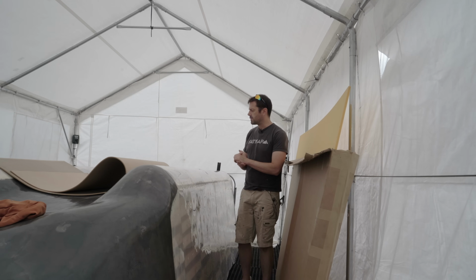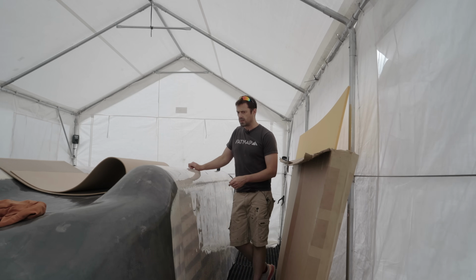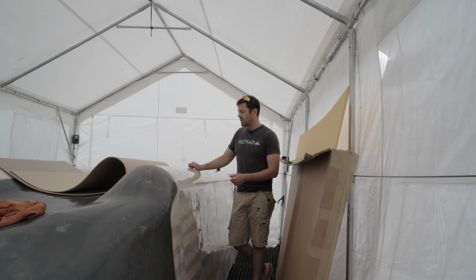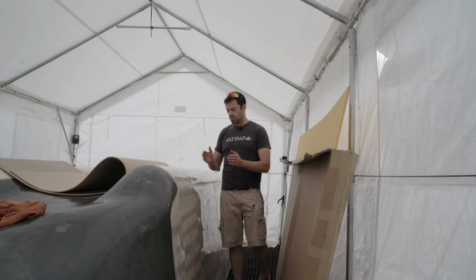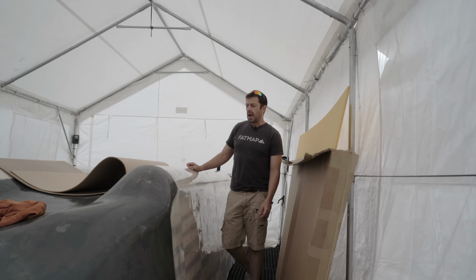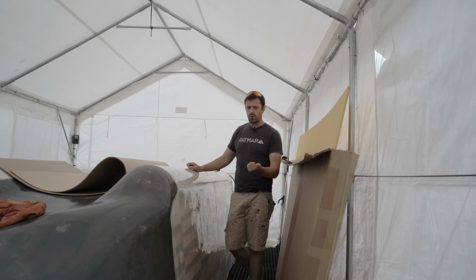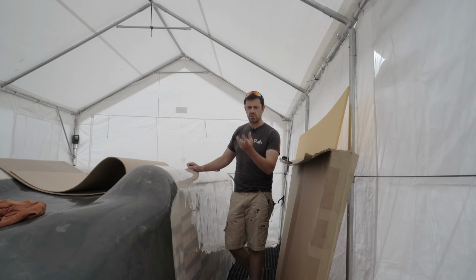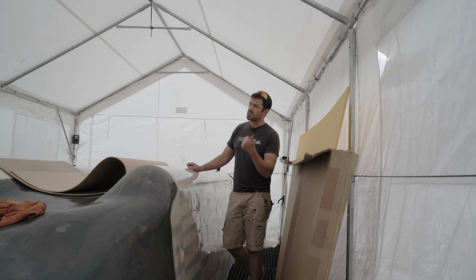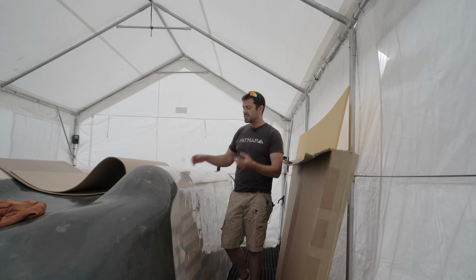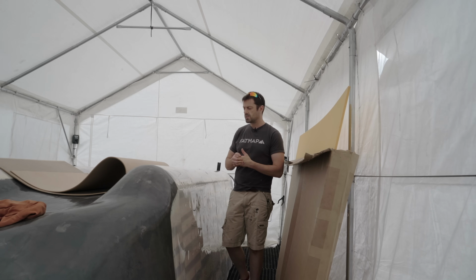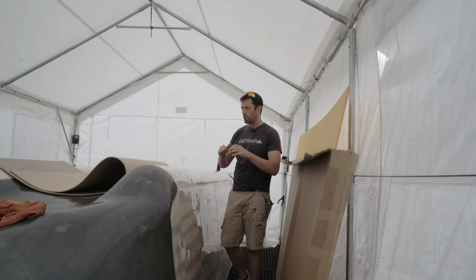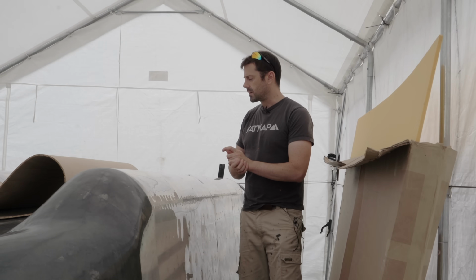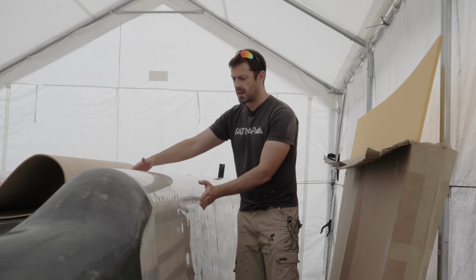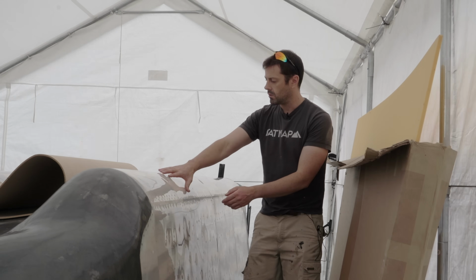So instead I'm going to make a form using MDF, and you might think, putting MDF in an oven, is that a good idea? The answer is yeah. I took some test sections, a piece of MDF about that big, and I put it in the oven at home at 80 degrees. I put it in there for an hour or two, nothing happened, no smell, no changing colour, it looked completely the same. I took it up to 90, 100, 110, 120, all in degrees Celsius, and I think I got up to 130, still absolutely no effect whatsoever, and so I would argue that this is perfect as a thermoforming mould. And you may think, well, how are you going to get this highly flexible stuff to stay in the shape of this tightly radiused area?